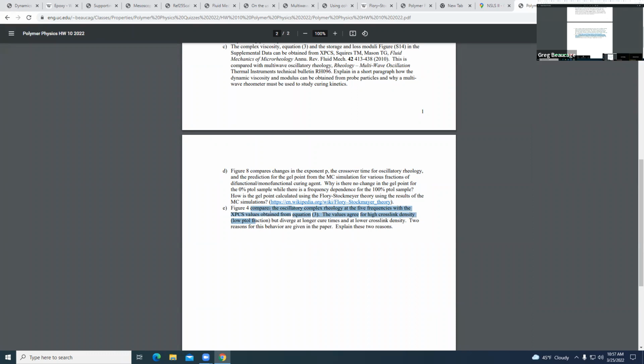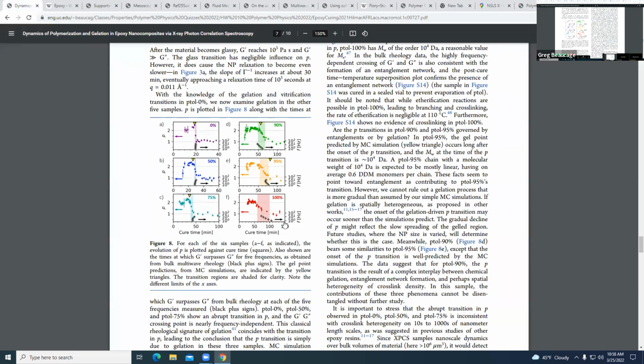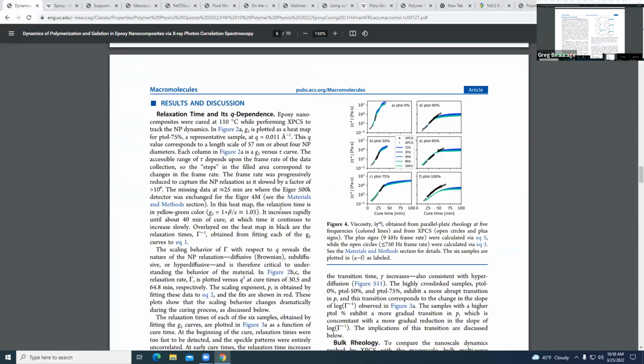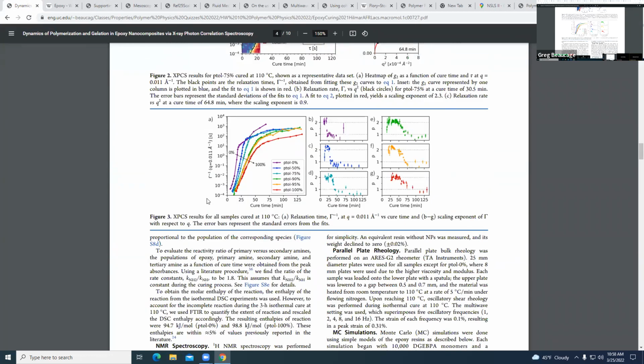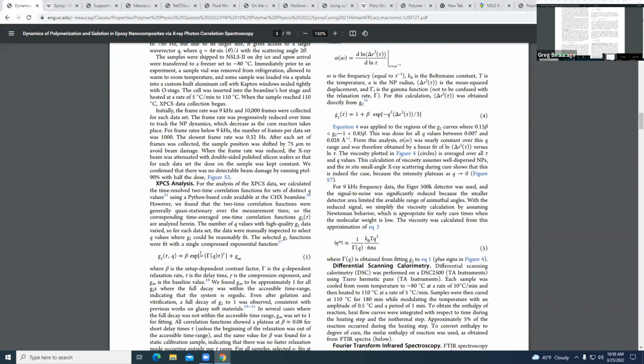Let's see. Figure 4 compares oscillatory complex rheology at 5 frequencies. The divergent longer cure times are the reasons for that. Figure 4. What is figure 4? That's figure 8. Figure 4. So the divergence is because as you go up in the linear one, it becomes more linear and it's got this spectral dependence, but there's also this transition here because of the evaporation. He mentions it in the paper. That one isn't really a big deal. So anyway, there's a lot you can get out of this paper, but just glancing at it, it's probably worthwhile. And it's got this kind of dynamic light scattering function in it. So it's got a lot.